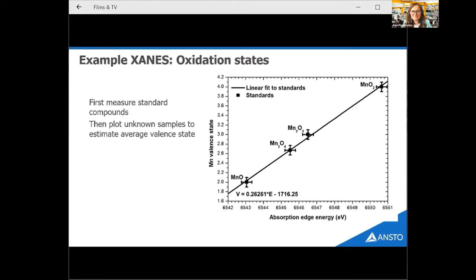So practically at the beamline, we always measure some known reference materials. And in this case, we've got compounds that represent manganese in the 2+, 3+, and 4+ oxidation states. Once we've established this, we can then measure unknowns and simply plot them on this line to work out what their average oxidation state is.